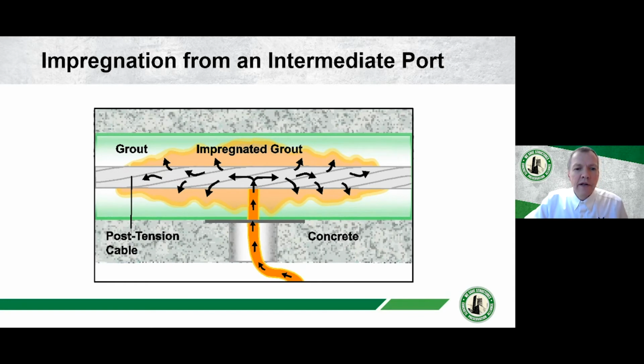If the end of the tendon isn't available, then you're going to typically do this work from some intermediate location through a port, and the material will be introduced at that location. The material in these situations generally is going to go both ways from the intermediate port. Again, the principal transport mechanism is inside the strands themselves, and then from there it's soaking between the wires into the surrounding grout.